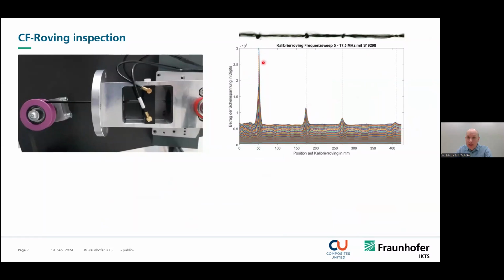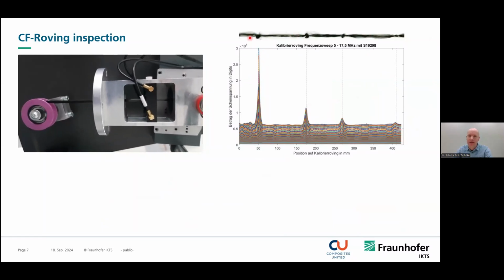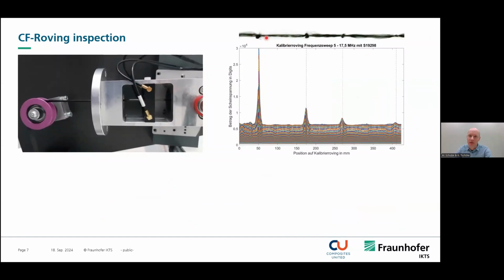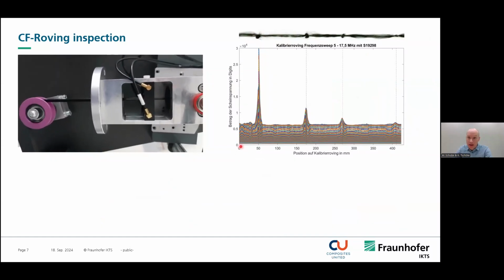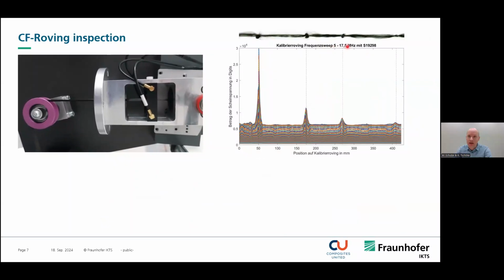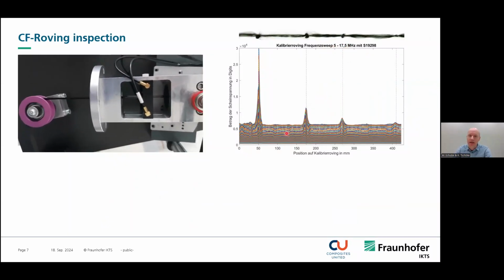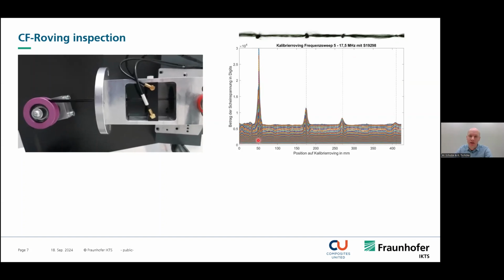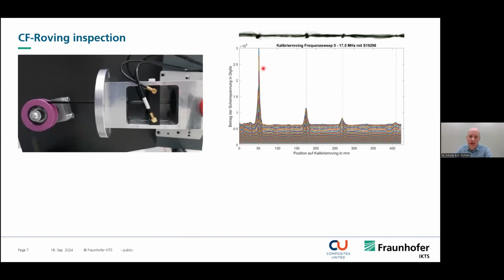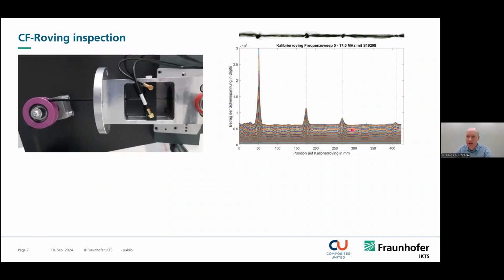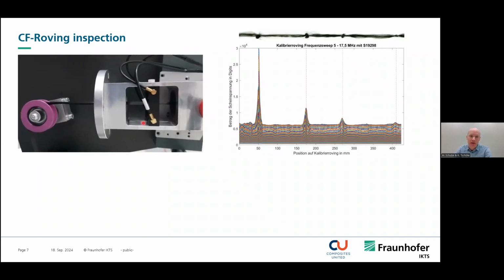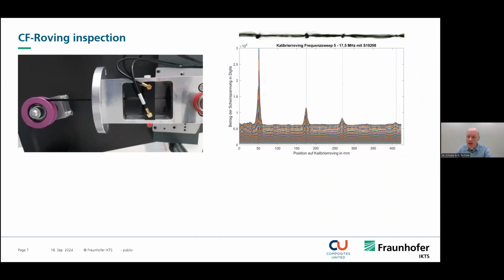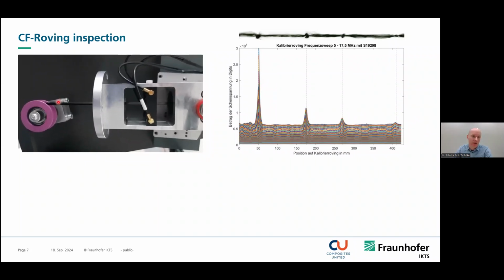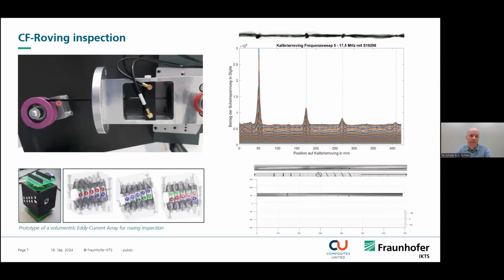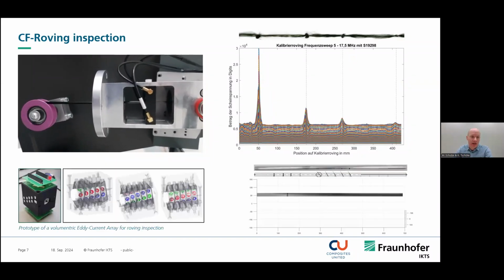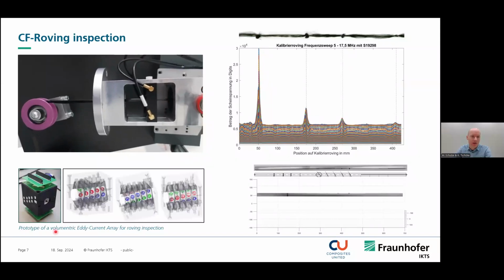Here, this is a very, very simple demonstration sample. So we make some knots into a roving, and by the summation of frequencies, in this case 5 to 17.5 megahertz, we generate an integral over all frequencies. Then here you see these knots very easily. But this method is also able to measure and to characterize the coating of such a roving.